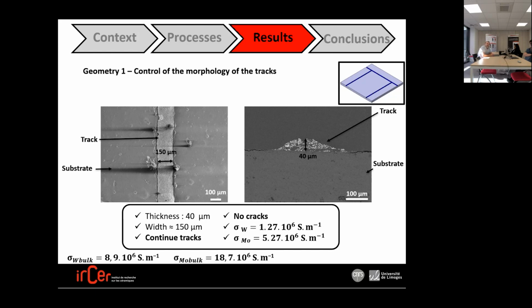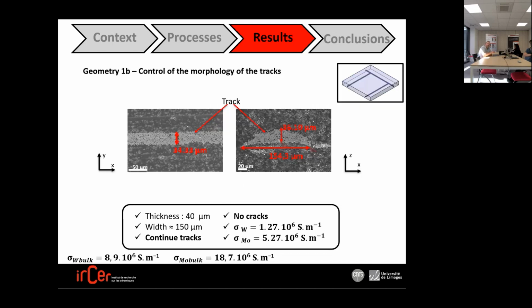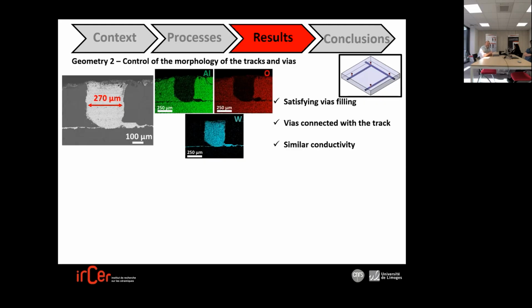So it's good, it works, and then we tried to make tracks that are inside the alumina substrate. As you can see here, the width of the tracks is about 35 micrometers, and the height of the tracks is about 36 micrometers. There is good continuity of material between the alumina and the metal, and the tracks are totally conductive from one side of the part to the other. Here you can see another type of geometry with a vertical via in order to connect the inside tracks of the HTCC part with another component, for example. We can see that we are able to fill vias. All the vias are connected with the tracks, and we have a similar conductivity.